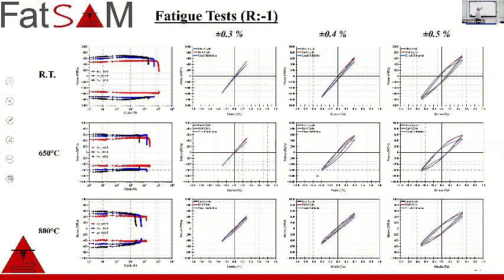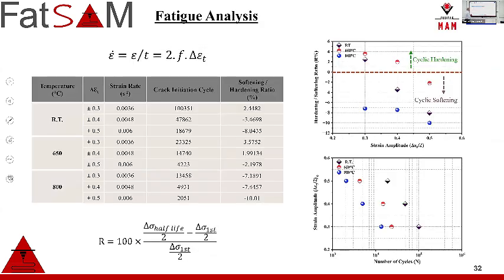At low strain levels, we didn't see any deformation, but for high cycles, because this is quick, after a certain amount of time, there are uncontrolled deformation mechanisms and fracture mechanisms for these materials. I will show some microstructures, and with the strain ratio increase, some strain energy is observed from the first cycle to the crack initiation area. These are the strain rates calculated for each material, and the crack initiation cycles.